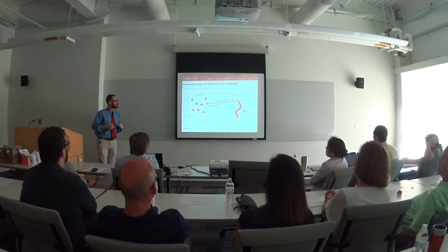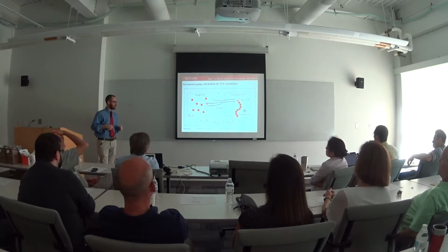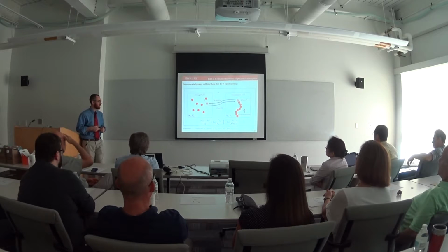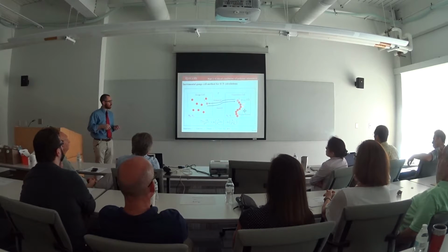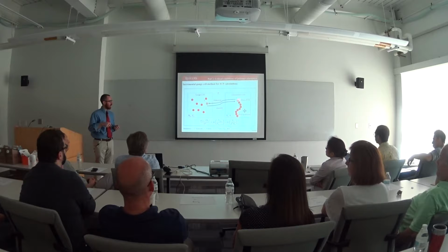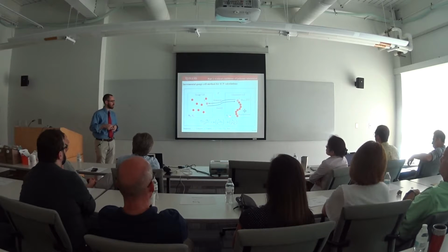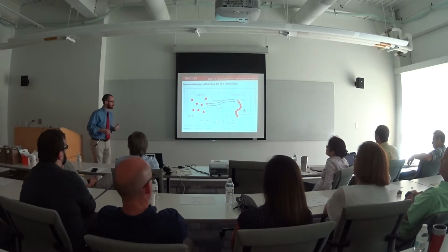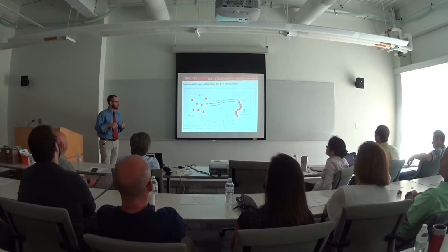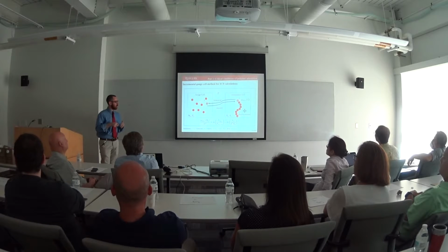To calculate the incremental chemical potential, we use something called the incremental gauge cell method, which is a Monte Carlo method that was developed in our group and expanded upon by a previous PhD student in our group, Chris Rasmussen. In the incremental gauge cell method, we have our simulation cell, which holds our polymer, and it's in thermal equilibrium with a gauge cell of free beads, which can be removed or inserted to the end of the chain. The total number of molecules in both cells is constant, as well as the temperature and volume. At equilibrium, we're minimizing the Helmholtz free energy. To calculate the incremental chemical potential, we actually don't need to know what's going on in this cell at all. We can just determine the probability to have any number of molecules in our gauge cell.